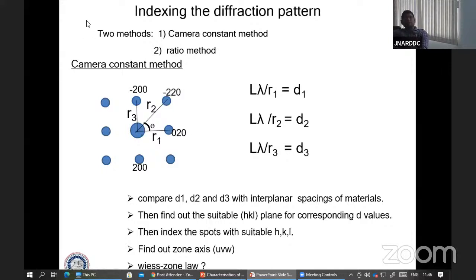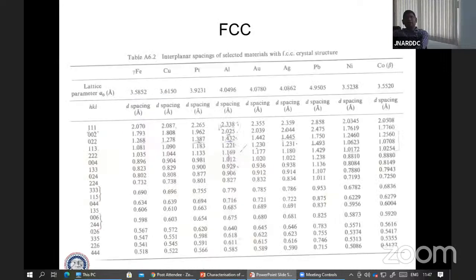Suppose you have a diffraction pattern like this. You will get a micron marker here in 1 by angstrom, which is reciprocal space. That scale will already be given on this diffraction pattern. You have to measure R1, R2, and R3 here by some software, or manually, and put R1, R2, R3 in these equations so that you get D1, D2, D3. These are the interplanar d spacings of the material. We have to compare these D1, D2, D3 with the data already available in the database. So these are the data available.